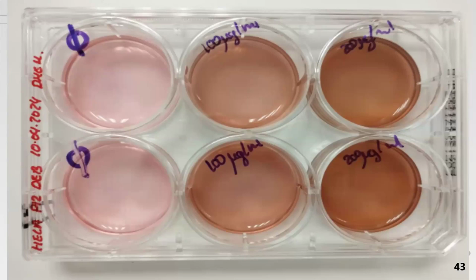In the first column, we just grew the cells as a control. In the second column, we incubated the cells with 100 micrograms of magnetic nanoparticles per milliliter. And in the third column, we put twice the number of magnetic nanoparticles per milliliter. And then we left them for 24 hours to incubate.